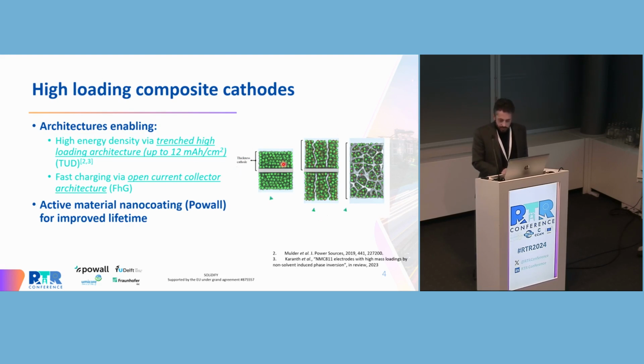The cathode is prepared according to a trenched architecture which was developed by one of our partners, where we can achieve a capacity up to 12 milliamp hours per centimeter squared. This trench architecture is particularly suited for accommodating the liquid electrolyte precursor. We may increase the thickness of the electrode and the loading without a substantial loss in terms of rate capability. Other two topics we have been working on are the optimization of an open current collector architecture, as well as the nanocoating of the active material particles in order to improve the cycle life in the cell.